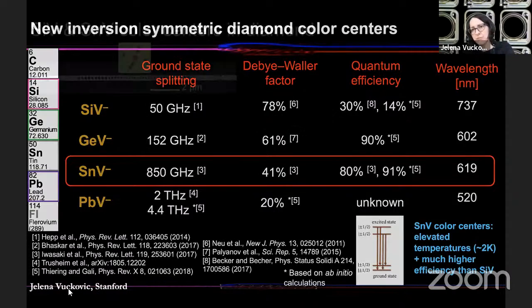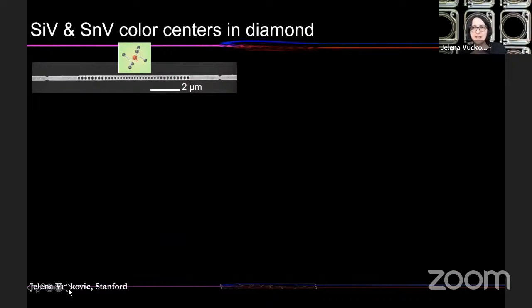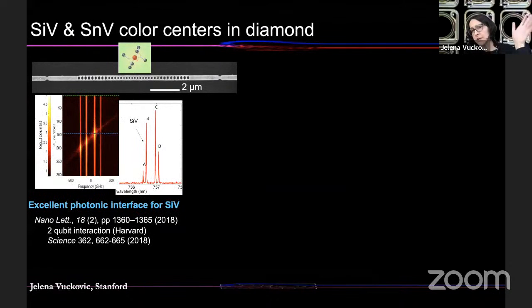And I'd like to give a one slide overview of the state of the art in silicon vacancies and tin vacancies, and then say a few words about the materials issues that I mentioned before. So with silicon vacancies in diamond, for 5 or more years, people have been working on embedding them in structures, with a variety of experiments. Excellent photonic interfaces have been demonstrated by quite a few groups, including groups at Harvard and our team at Stanford. It's much simpler, as I mentioned, to embed it into a cavity and show large cooperativity and strong Purcell enhancement than for, for example, nitrogen vacancy in diamond.